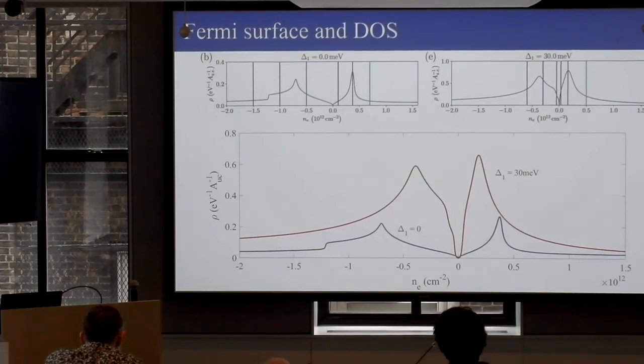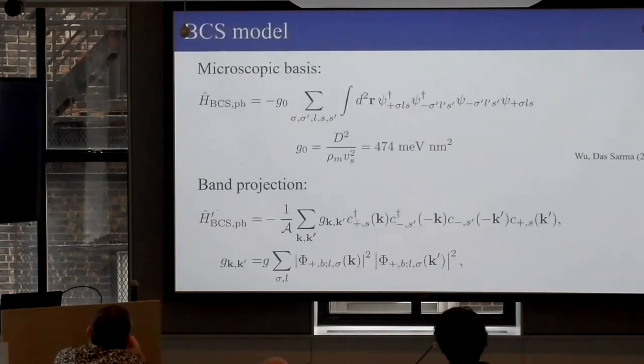And this was always Pablo's point, that if it's the kind of electron phonon mechanism we are talking about, superconductivity should be just around this. So we need a full calculation. I'll give away the story. What we find, it depends on some integrals. So superconductivity lasts over some range. It doesn't just disappear right beyond this. It's more stable than that.